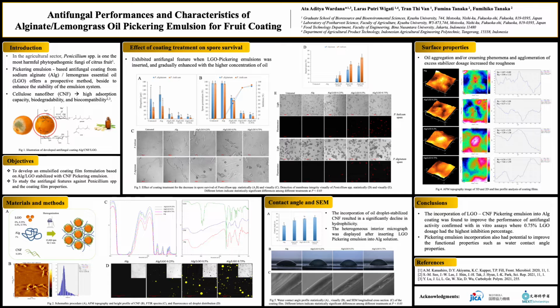As seen in figure 2b, cellulose appears in a typical rod-like shape and forms some clusters. To know the interaction of each material, the coating films were analyzed using FTIR with the ATR method. As seen in figure 2c, there was a decreasing trend of intensity when emulsion was inserted. It indicated that the hydrogen bonding interaction between the alginate and Pickering emulsion may disrupt the molecular network between individual beta-D-mannuronic acid and alpha-L-guluronic acid. And the greater intensity appeared for a higher level of oil, indicating enhancement of hydrogen bonding interaction between the components and hydroxyl groups from essential oil and cellulose.